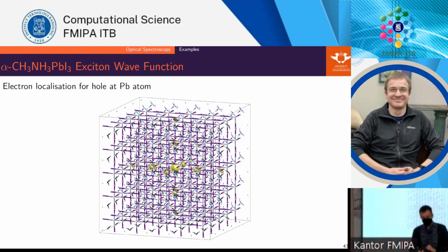So for example, if we have a very localized electron hole pair, that is going to recombine probably very quickly, right? So basically recombination is when both are at the same site. That is bad because I can only extract the electron if it lives long enough to reach the electrode, right? If it combines with its hole before it reaches the electrode, we may have had a high absorption rate in the solar cell, but we cannot extract the energy, right?